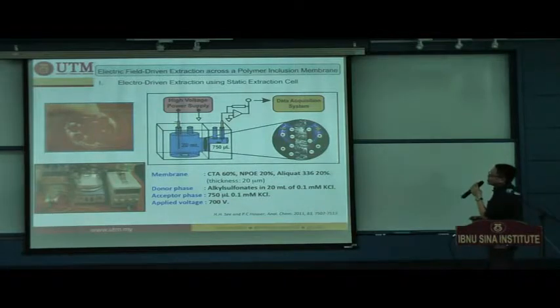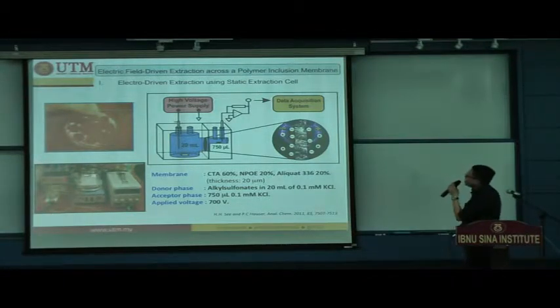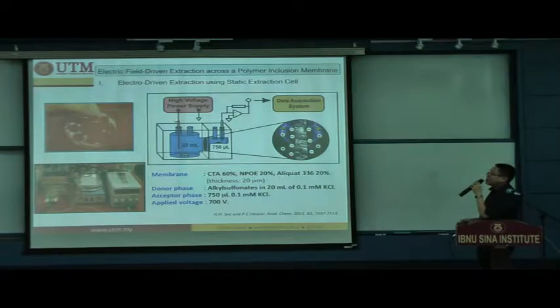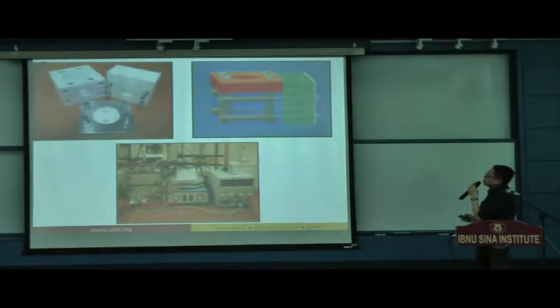And the membrane is cut and sandwiched between these blue blocks. Over here is the sample solution, which contains 20 milliliters of sample, and this is 750 microliters of acceptor solution. So we are expecting all the analyte to migrate from the sample phase across the membrane into the acceptor phase. After the extraction, we are going to quantify the amounts of analytes inside the acceptor phase by using capillary electrophoresis. This is the extraction cell setup, which is made from PTFE.